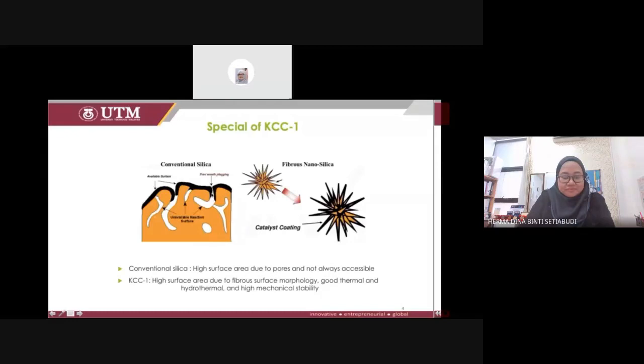If you compare with the conventional silica, this is the conventional silica, this is the fibrous nanosilica. Both of them have a high surface area, but with the conventional silica, due to the pores, sometimes the reactant cannot enter, not always accessible to the reactant, but this is different with the fibrous nanosilica. Of course, due to the fibrous morphology, it has a high surface area. And then the reactant can enter in between the fibrous structure, and then can proceed the reaction in high performance.